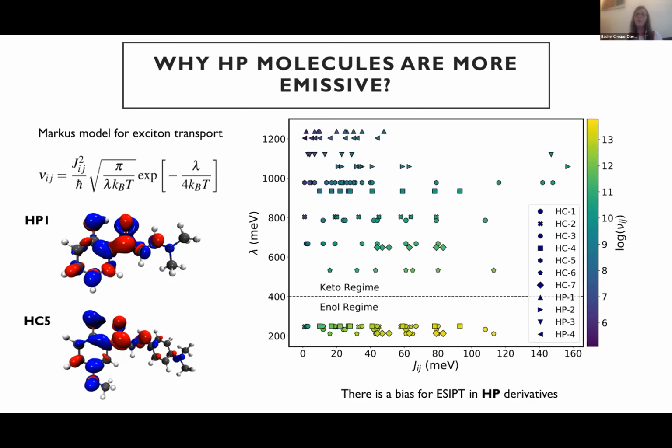And in this case, you may have some competition between formation of the keto form and the electron transfer between the systems. So if you want to achieve a large emission in this kind of systems, you need first to make sure that the conical intersections in your system are not accessible. But you also need to make sure that the proton transfer process is extremely likely, so you are able to stabilize the system once you are in the keto form, once you are in the excited state.